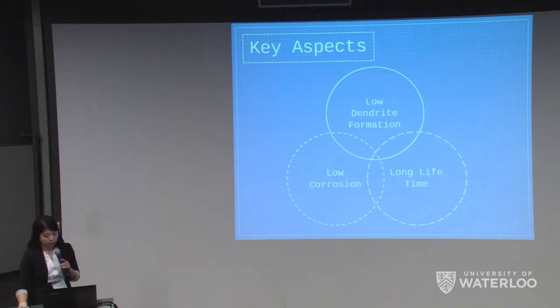Dendrite formation is also another problem with the use of a gel electrolyte. Dendrites are microscopic fiber-like structures that form on the surface of the anode and are caused by the deposition of the cations. Dendrite formation itself is not desired, but uniformity in dendrite formation can be less critical towards the battery performance. Such morphology would be that the dendrite formation would be flatter compared to tree-like growth.